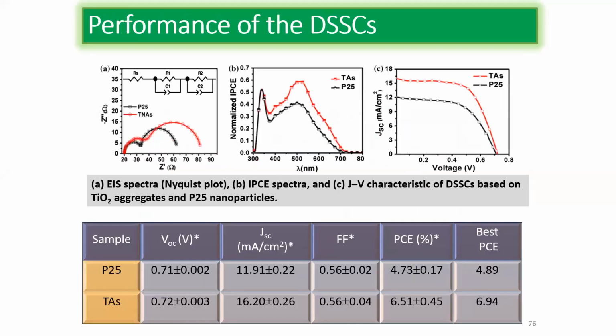So when we use this particle, whether it is working in DSSC or not, we can clearly see that at longer wavelength, it works very well compared to the normal particles. And the efficiency enhancement is also very good, from 4 to around 5 to 7%.